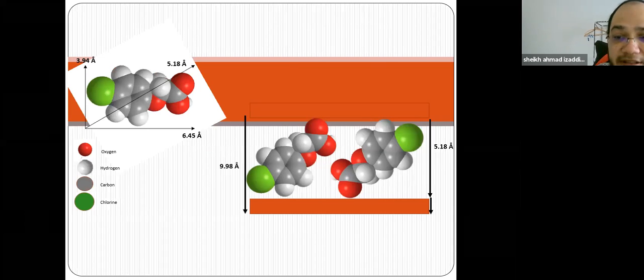Okay, this is the illustration of the molecular structure and the proposed spatial orientation of calcium aluminum 4-CPA LDH nanocomposite. As we can observe from the increase of basal spacing of the nanocomposite, the gallery height of the interlayer region of the nanocomposite, after subtracting the layer thickness of the calcium aluminum LDH, which is 4.8 Angstrom, is 5.18. This can be deduced that the anions were oriented in a monolayer arrangement in between the interlayer regions of the LDH due to the consideration of 4-CPA molecular structure and charge orientation.